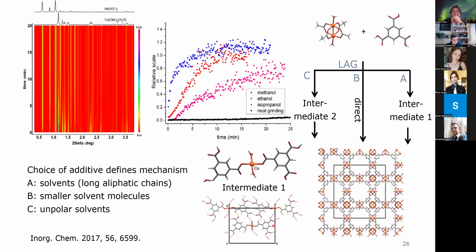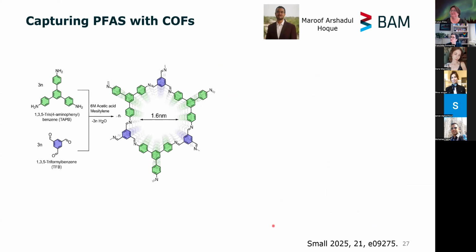Yeah, maybe switching gears a bit and looking into covalent organic frameworks. This is a recent work by one of my PhD students working in the CRC, where we focus on fluorine interaction. And here one of the very good fluorine interactions would be to have an adsorbable material for PFAS. And here you can see the reaction to form a COF material. It's a 2D imine COF that we generated here, and you can see the pores are just large enough to host the most prominent PFASs.